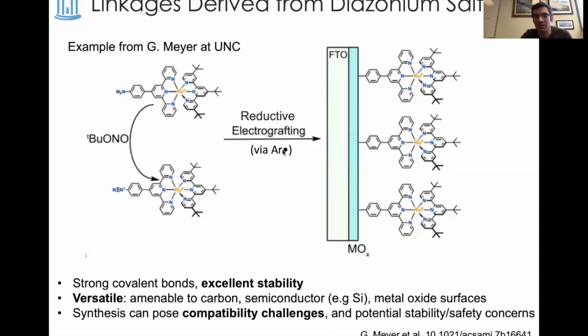One limitation is the need for an electroactive surface. So if you need to do an electrochemical reduction to trigger the surface attachment, you need to have a conductive material support. And then there's some compatibility challenges potentially, that the conditions, for example, to form a diazonium may not always be compatible with the catalyst you're interested in. You may decompose the catalyst, or you might have concerns about safety or stability involving these relatively high energy intermediates.